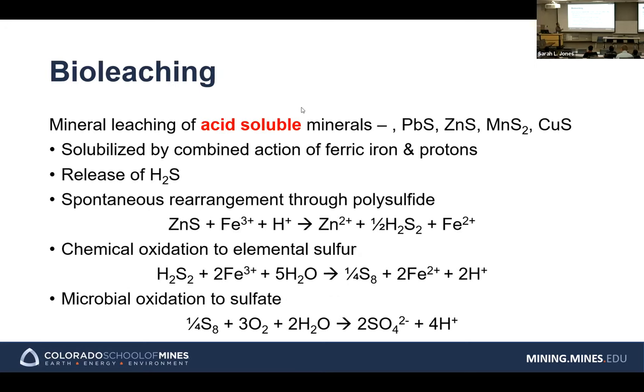And the next term is bioleaching. So bioleaching is, as it says, mineral leaching of acid-soluble minerals, such as lead sulfide, zinc sulfide, manganese, and copper sulfide. So if we have acid, these materials can be dissolved. So we can have lead, zinc, manganese, and copper in an aqueous solution, solubilized by the combined action of a ferric ion and an acid. And then during that process, you could release H2S gas.